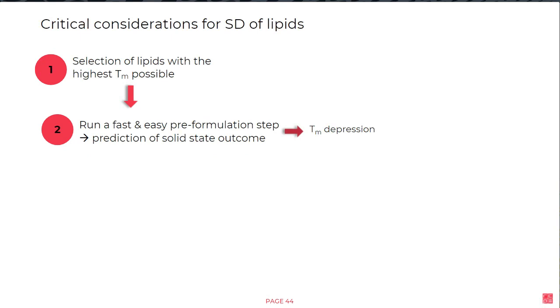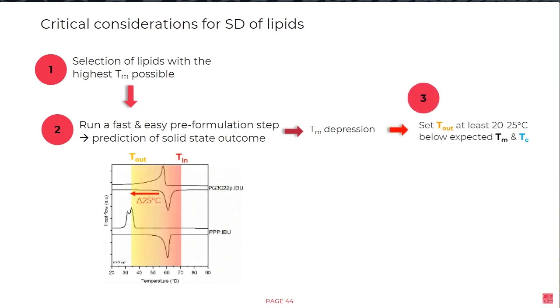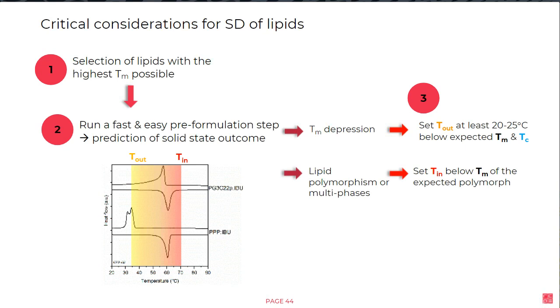If we find there is a melting point depression or polymorphism, we have to set the outlet temperature at least 20 to 25 degrees below the expected melting or recrystallization. For polymorphic lipids or multiple phases, it is better to avoid melting in the system, meaning that setting the inlet below the melting will be the ideal situation.